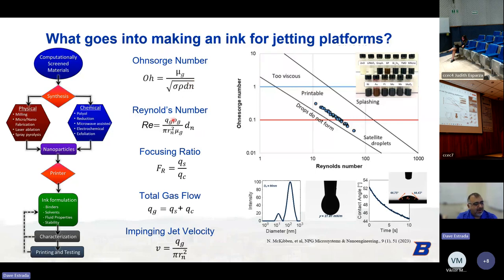On the Reynolds number side, we have to take into account the gas density, the gas flow, and the cross-sectional area of the nozzle, and then the viscosity is down here in the denominator. And here's the diameter of the nozzle. When we plot these against each other, we end up with this window here, where if the ink is too viscous, it won't print. If it's not viscous enough, we get a lot of satellite droplets forming and a lot of splashing, and that may affect the quality of the printed features.